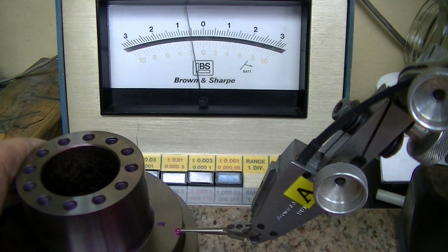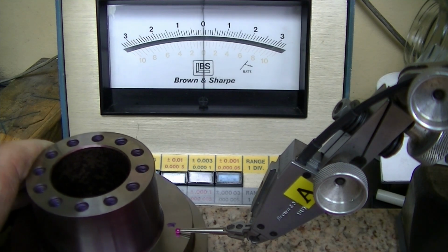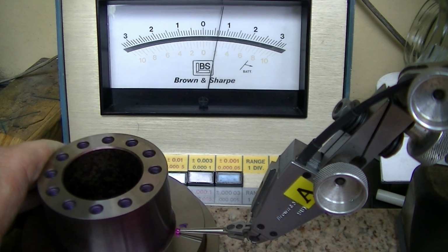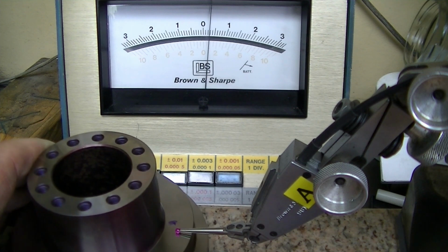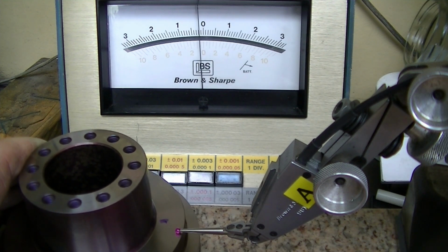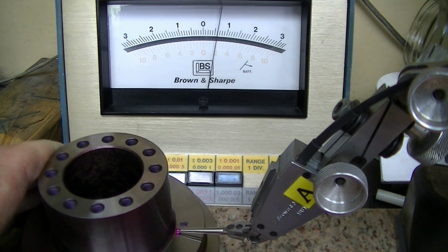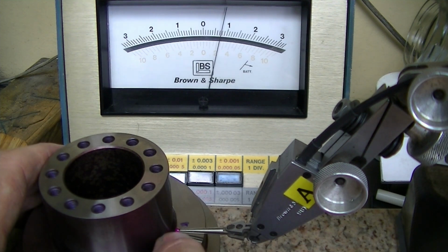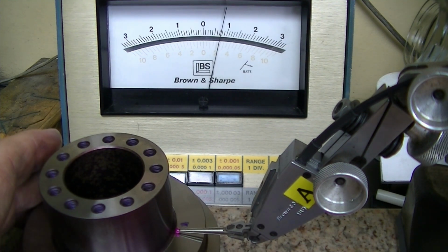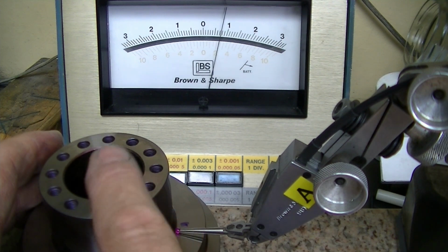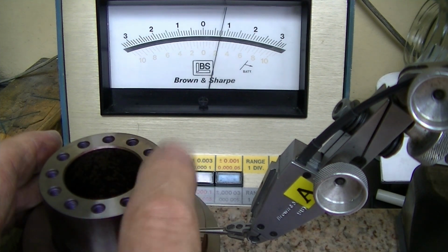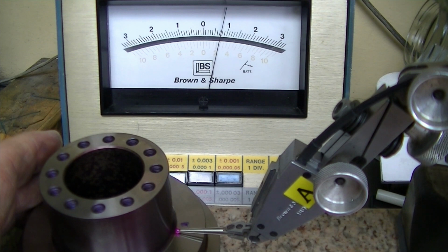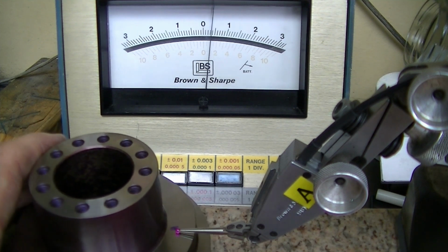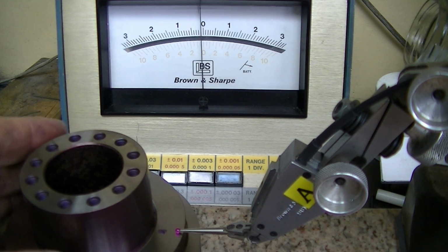You'll notice down here that we've got some taper, or it's conical. It's high in the center, low on the outside, and that is from the fact that I'm taking a full half-inch wheel, diving in here and moving out, and that's not an ideal situation. Where these other surfaces we could get completely off on the inside, use the full wheel width, so none of the shape of the wheel got into the grind. But that doesn't matter because it is going to be lapped anyhow.